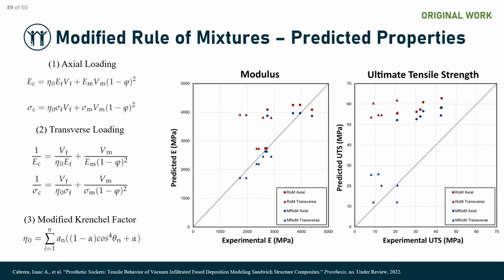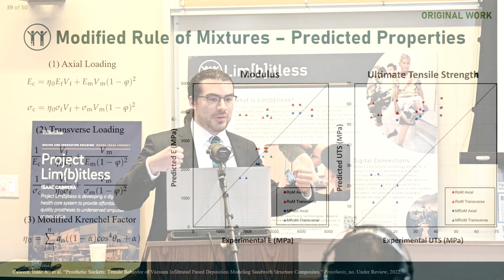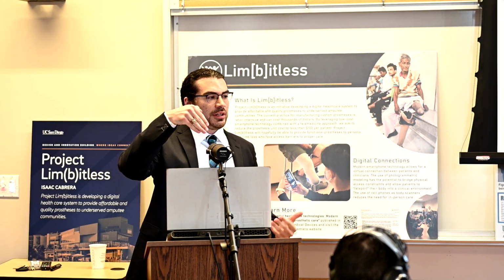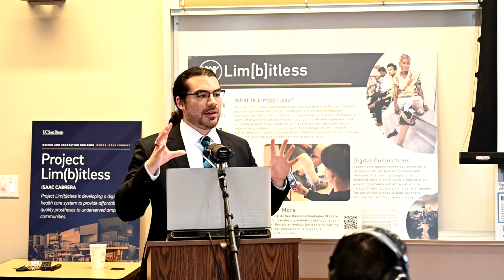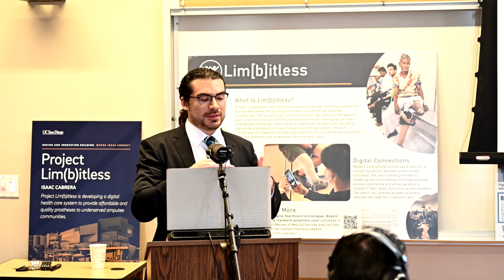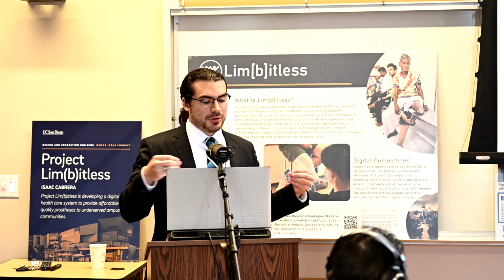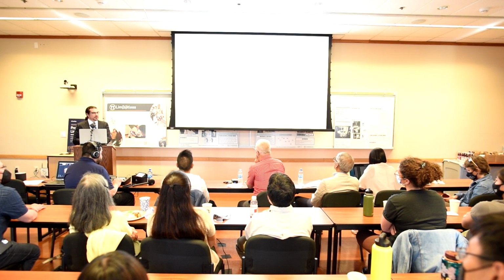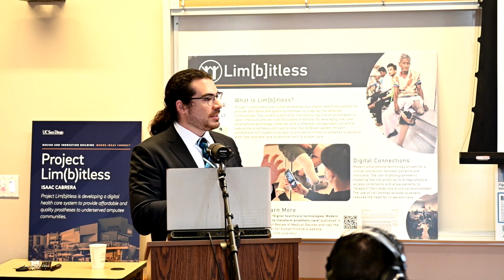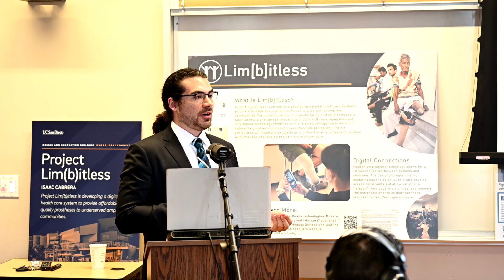And then this n naught is the Krenchel factor, but I modified it slightly. The Krenchel factor is a measure of fiber orientation efficiency for composites. If you have composite materials, you have fibers and you have a matrix. Depending on the orientation of those fibers, you'll have a reduction of material properties: if it's parallel to the loading direction, it'll be strong; opposite the loading direction, it'll be weak. But the traditional Krenchel equation basically says that your contribution is 0 if it's loaded transversely, which of course is not true. Our stiffness was not 0,